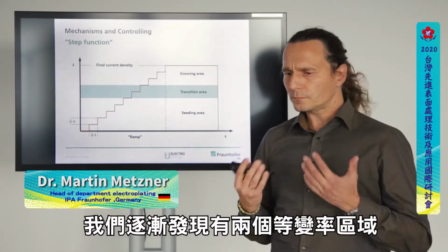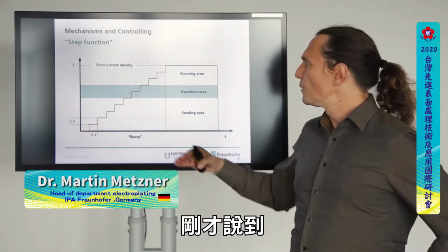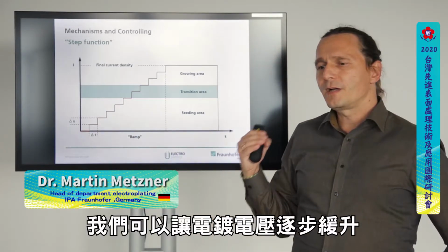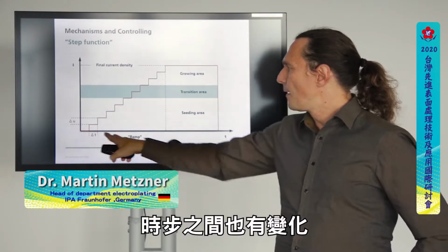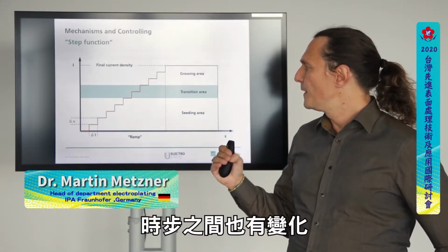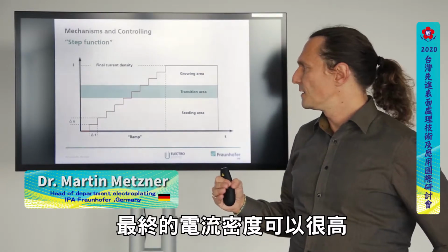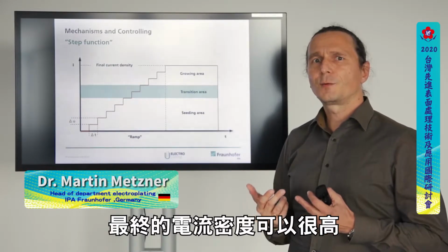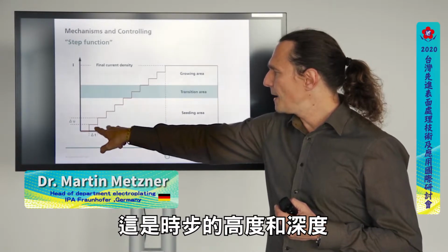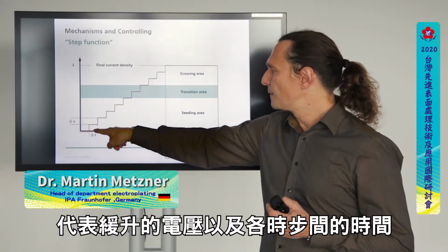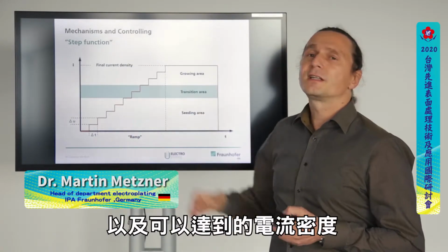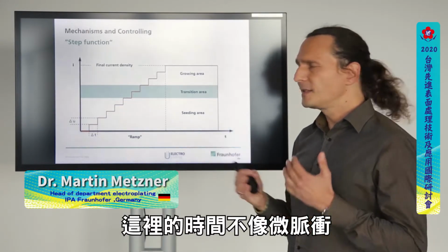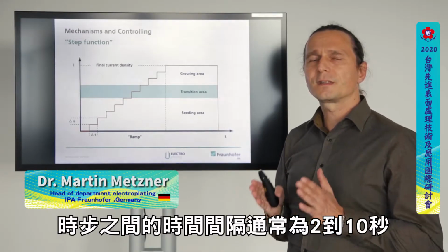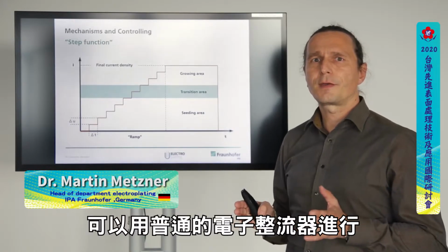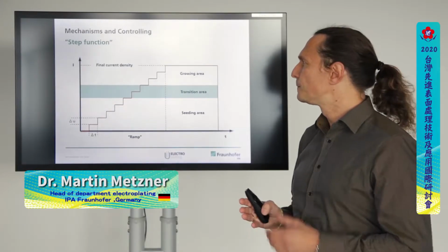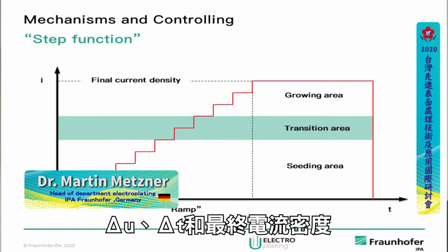And what we found out over the time is that we've got two areas of our ramp. As I told you before, we can control it by ramping up the plating voltage step by step. We have another variation in the time we have between the steps, and we go up to a very high final current density. So we've got three parameters we can deal with: the size of the steps in height and in depth, which means the voltage we ramp up, the time we have between the single steps, and the current density we can go to. The time between the steps, this is not something like a micropulse, is typically between 2 and 10 seconds, something you can do with a normal electronically controlled rectifier. So we've got three parameters: delta U, delta T, and the final current density.